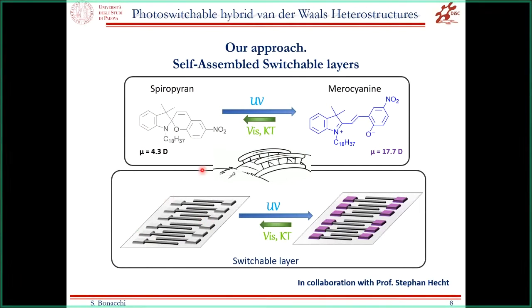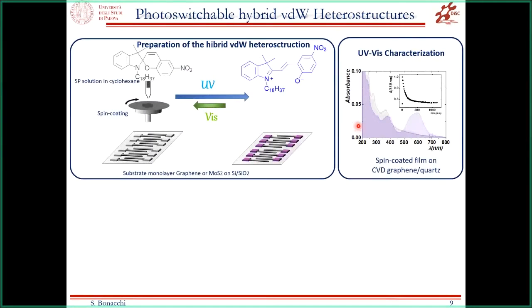So we designed this kind of spiropyran molecule, and we try to understand if we can use this photoswitchable unit from spiro to merocyanine and then back to the spiro form to induce a photoswitchable tuning of the optical and electrical properties of this van der Waals heterostructure. And so basically we use a quite simple approach.